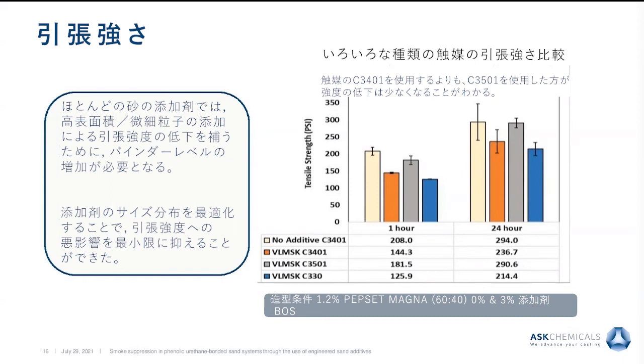So the tensile strength, and this is well known that for most sand additives, because they are finer powders, and the nature of these powders is they have high surface area, they're fine, it is known that they could have a reduction in tensile strength. And so that's why when you develop a sand additive, you have to do quite a bit of homework on trying to adjust the distribution so it's less detrimental to the tensile strength. So let me show you here two different time points for tensile strength. We picked 1 hour and 24 hours.